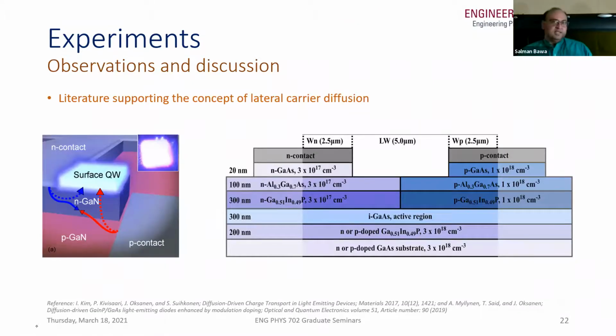And so we asked ourselves, has this ever been reported in literature? And here are two pieces of literature that we found that talk about the concept of lateral carrier diffusion, but in direct bandgap materials such as gallium nitride. So if you look at the figure on the left, you see a gallium nitride PN junction produced, and then there is this quantum well structure that is being developed here. So there is some radiative recombination happening at the junction, but then the electrons and holes also diffuse to the quantum wells where they radiatively recombine.